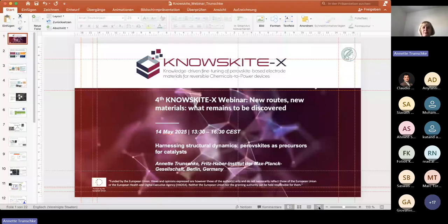And if we, for example, look at the O1s spectra, and here this is only in oxygen, the pretreatment of this catalyst, while we go in oxygen from room temperature to our reaction temperature, 270 degrees Celsius, we see that the profile of this O1s signal is changing very much. So we change our oxygen species, and to find out what these oxygen species are, we did a lot of fitting. I come to this in a moment.